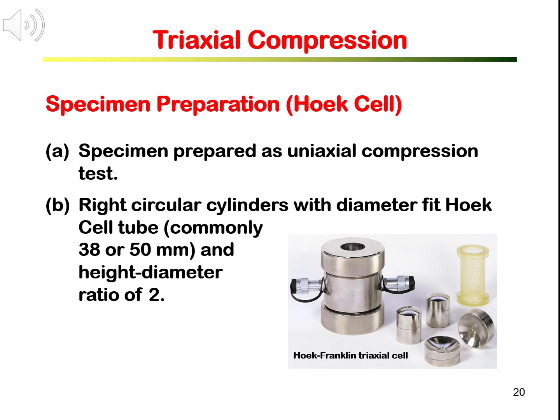Specimen preparation for triaxial compression tests is the same as that for uniaxial compression tests. It is prepared into a circular cylindrical shape. For using the Hoek cell, the commercially available cells are either 38 mm or 50 mm. So the rock specimens are about 38 mm or 50 mm in diameter in order to fit in the rubber sealing sleeve shown on the far right in the photo. The length of the specimen cylinder is 2 times the diameter.